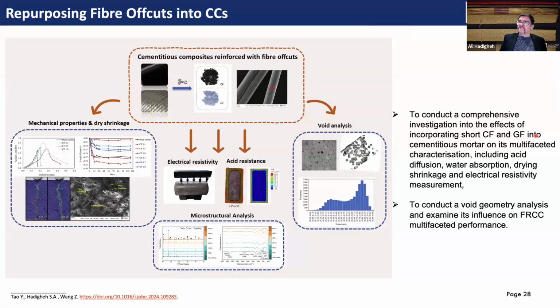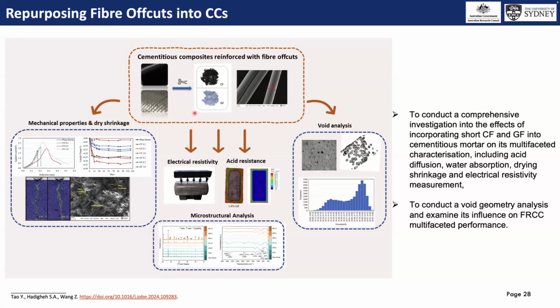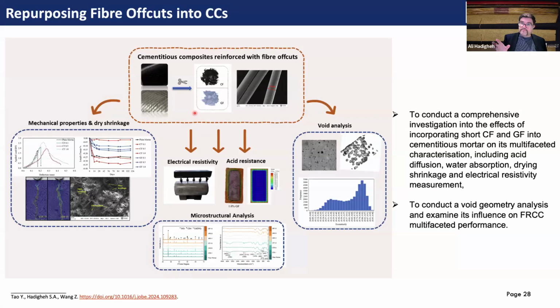The other work that we did was focusing on those offcuts that we mentioned. 30% are wasted during the manufacturing process. A lot of fiber offcuts are wasted during the process. So how do we deal with this? Basically, it's addition of fiber into concrete. But when we do that, we have to be very careful, because addition of fiber is good, improves the tensile strength, flexural strength, and possibly reduces shrinkage. But at the same time, it leads to formation of voids and increases the void content and permeability of the concrete.